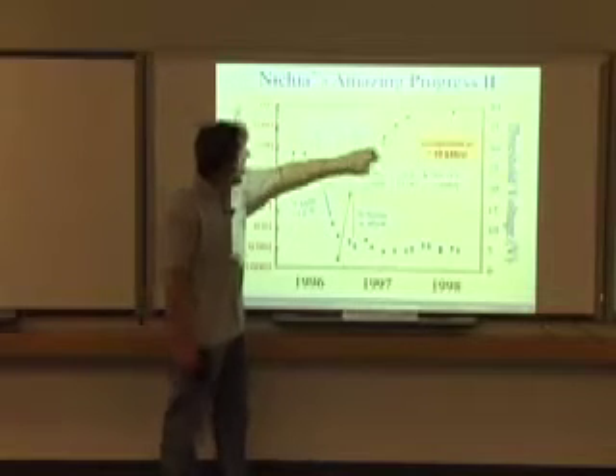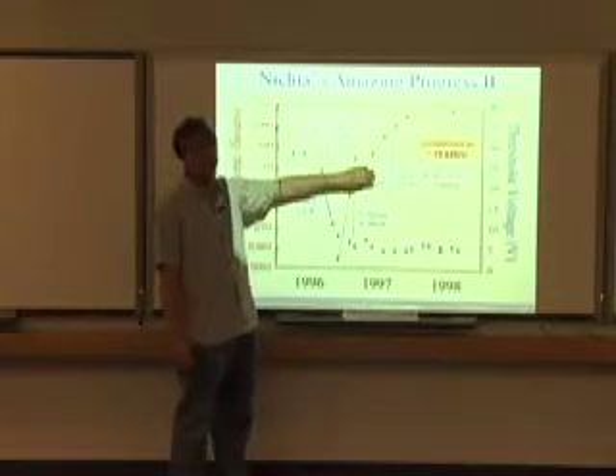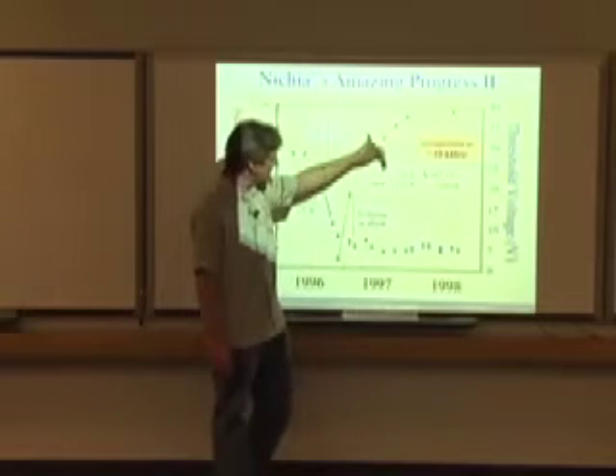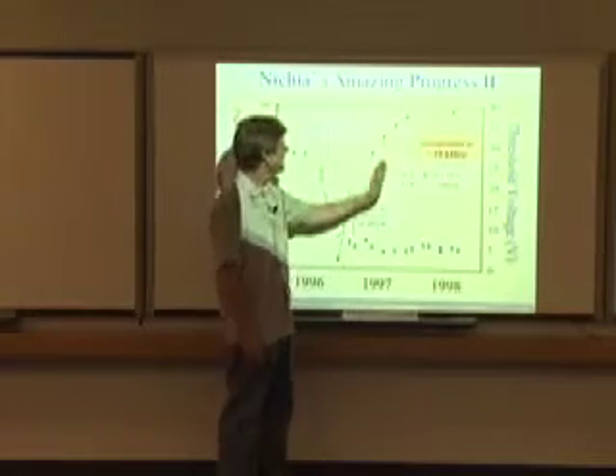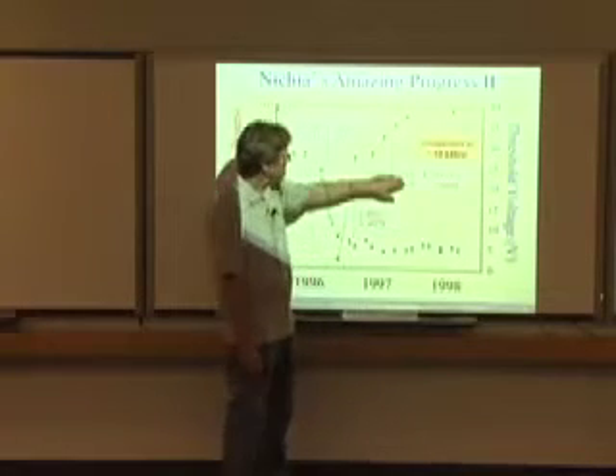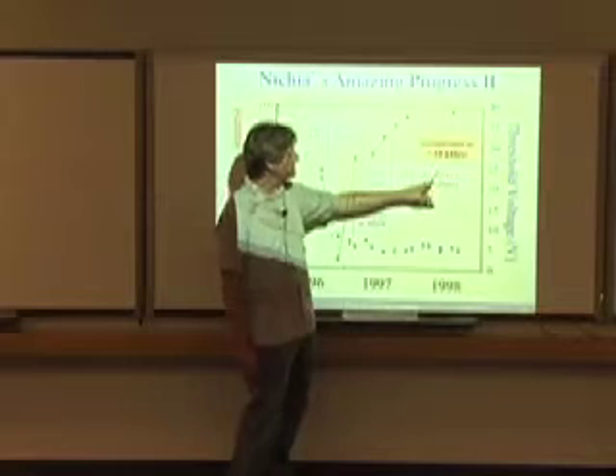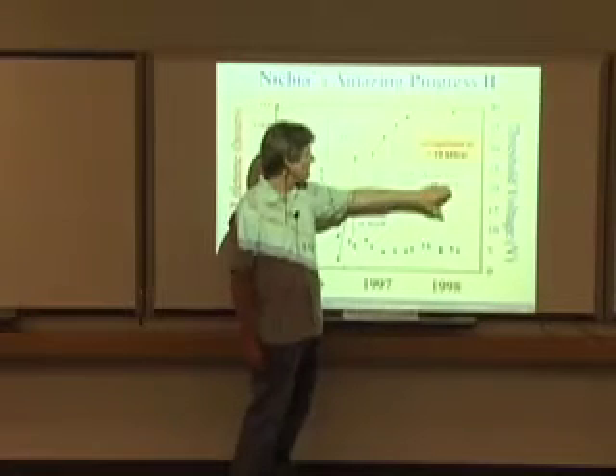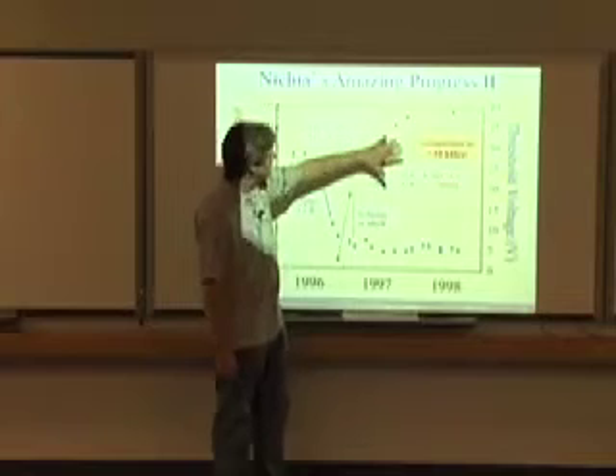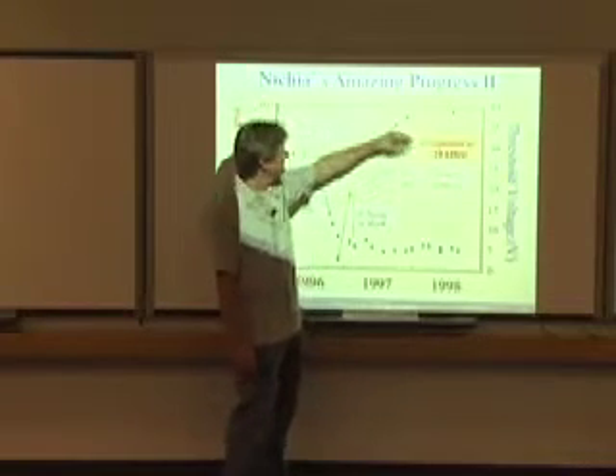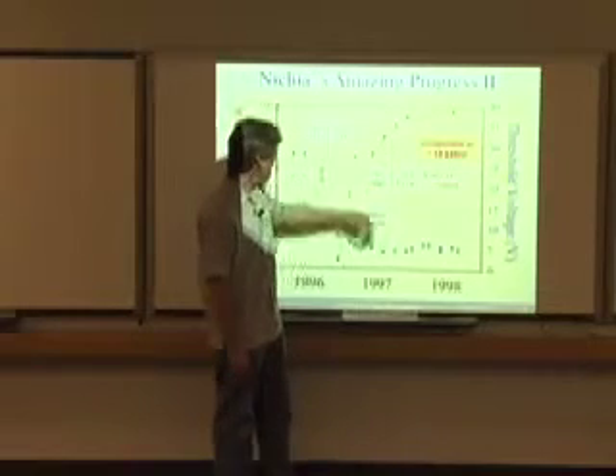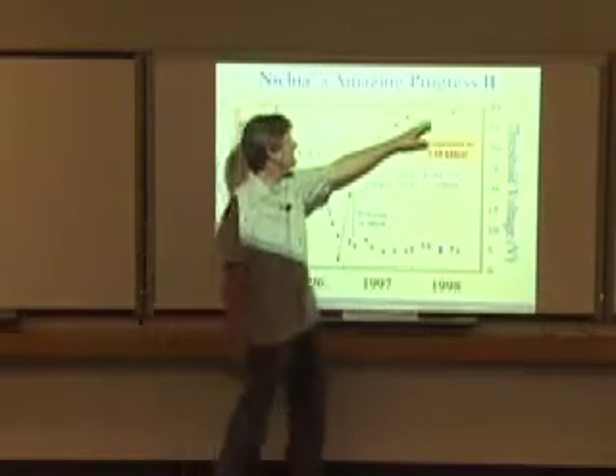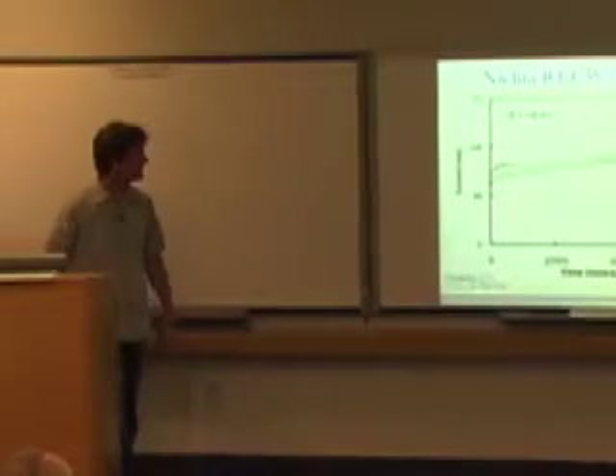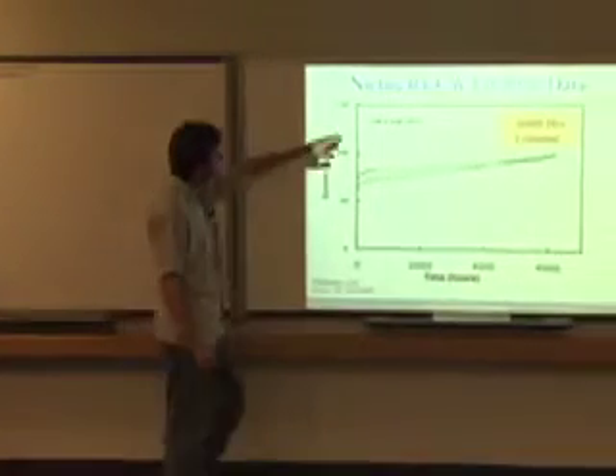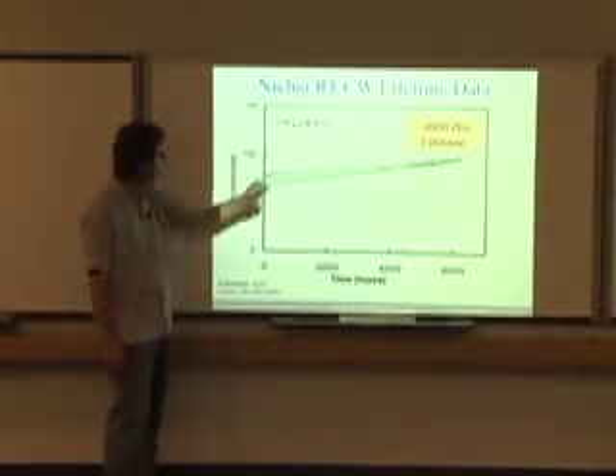above 10 hours here. And these different dots here are still using C-face sapphire, but at a later point, sometime in the middle to the end of 97, he transferred over to using thick ELOG structures, and also transitioned to using modulation doped superlattice structures for the P cladding layer that improved the P doping levels to drive the voltages down even more. And you can see that he was able to get extrapolated lifetimes of greater than 10,000 hours. The plot here is about 6,000 hours of CW lifetime. And this is an example showing CW for 2 milliwatts, constant power at 20 C.